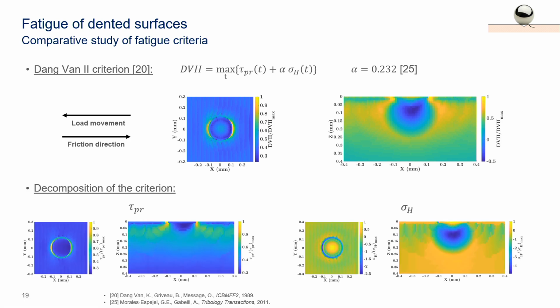This time we were lucky because we can see that the maximum criterion is at the surface, in front or behind the dent. And okay, one means the failure of the material. And again, you can make a decomposition. This is the effect of the shear stress, which is tau. You have again a constant, a parameter alpha, taken from the literature for this material. And this is the effect of the hydrostatic pressure, the mean stress. And okay, then this parameter is okay.